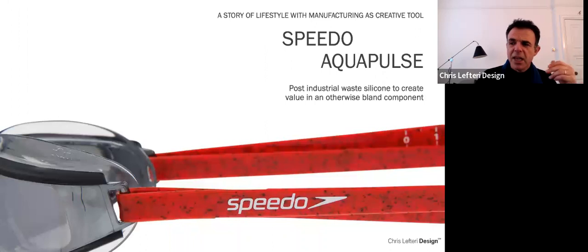And this one is one of my favorites, because they don't promote this as a recycled material. They don't say, hey, buy these swimming goggles, we use recycled plastic. The black specks that you see in the headband are there because when they're injection molding the swimming goggles and making the black silicone around your nose and around your eyes, there are offcuts from that. They chop up those black offcuts from the silicone, and then when they're molding the red part for the head strap, they're mixing the black in with the red. Not only do you get this really nice, interesting effect that gives decoration to a part of a product that never really had any decoration, but you use less virgin red silicone. So this is becoming much, much more important. And as I said, I really like this one because they don't scream and shout about this incredible innovation.